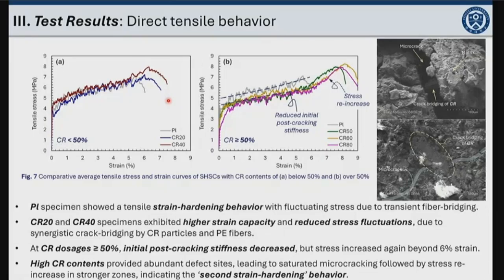This is caused by the decreased matrix cracking strength by crumb rubber acting as flaws, and the synergistic crack bridging effect of the crumb rubber and polyethylene fibers, as you can see here. The crumb rubber effectively bridges the cracks, the micro cracks.